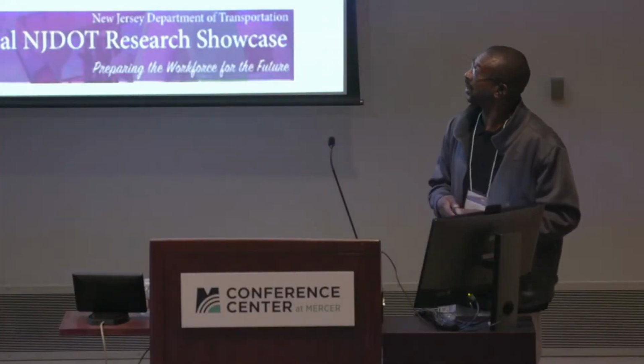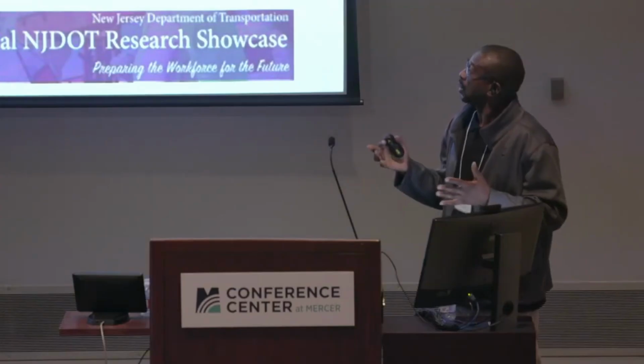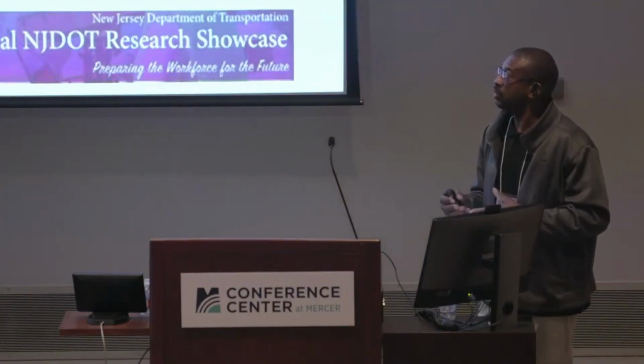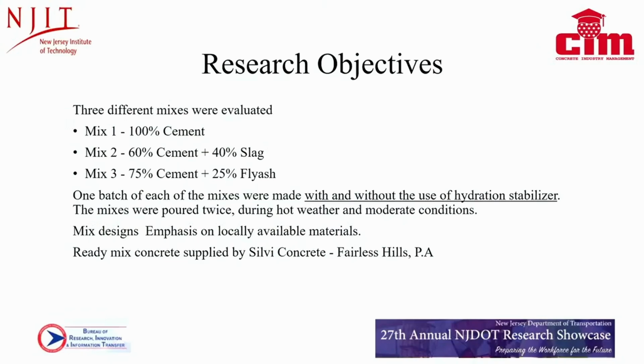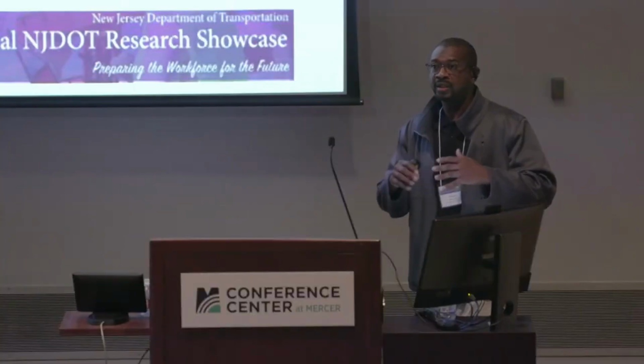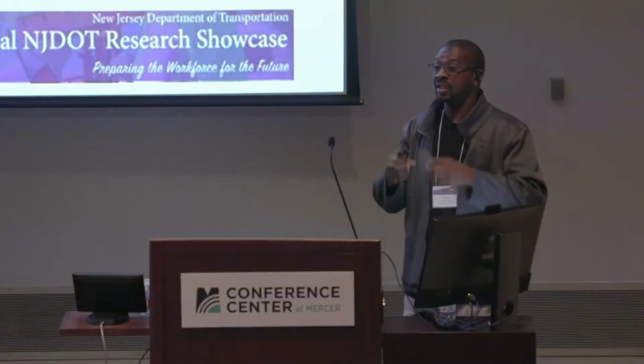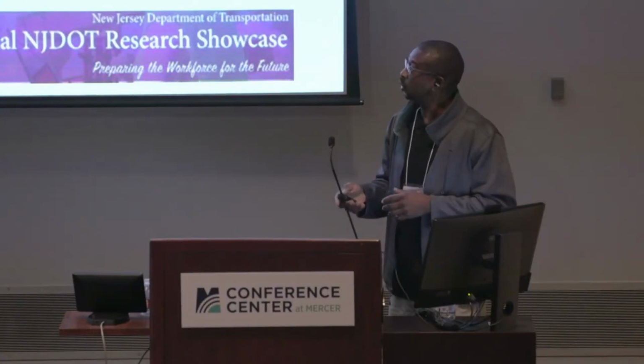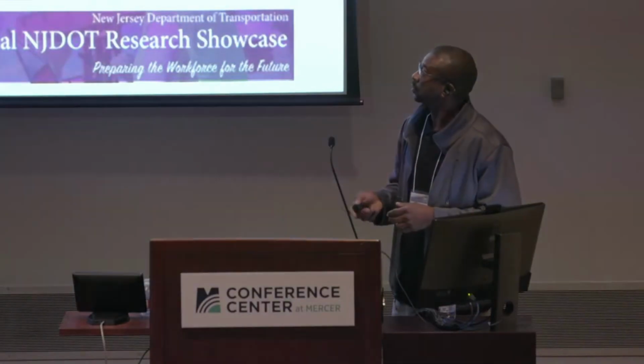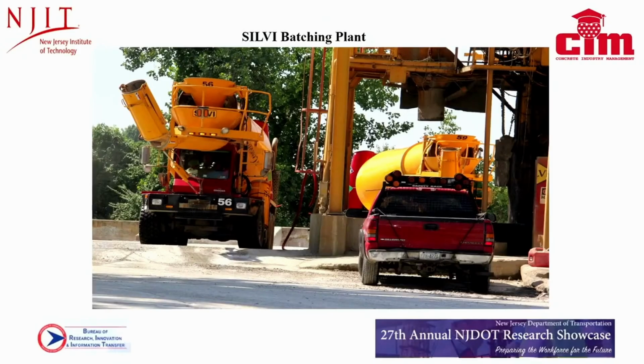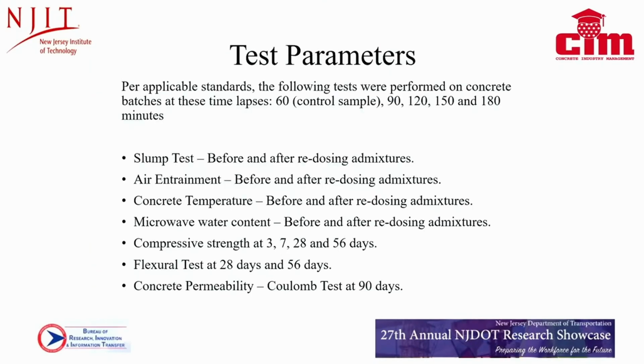All right, so I'm going to try my best with this presentation. Part of the research is we did 3 mixes. Mix 1, control, 100% Portland cement. Mix 2 and mix 3, utilizing cementitious materials, in this case 40% slag and 25% fly ash. We actually did the research at an actual ready-mix facility so we could emulate realistic results as opposed to doing it in a small mixer in a lab, right? So we chose that option, so we had those sponsors and so on. This was in Pennsylvania at Silvi Concrete.